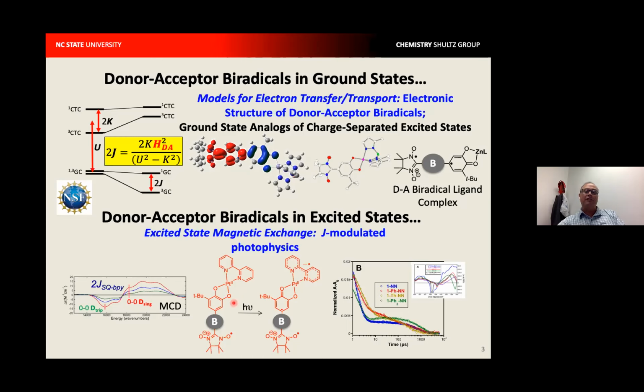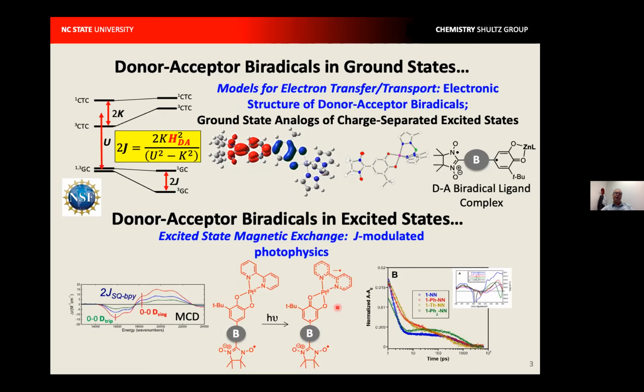And these complexes all have visible wavelength catecholate to bipyridine charge transfer bands, so that excited state now has a semiquinone bipyridine radical anion character. But the donor half of the molecule now, if we covalently attach a nitronyl nitroxide radical, has the same charge and spin distribution as the zinc complexes that I mentioned up here above. And so, because of the similarity in the spin distribution here, we understand what the exchange coupling is in the excited state between the semiquinone and the nitronyl nitroxide. And using other spectroscopic techniques, we can spectroscopically measure what the exchange parameter is between the semiquinone and bipyridine radical anions. So we have three spin excited states where we have an experimental handle on both of the important dominant exchange pathways.